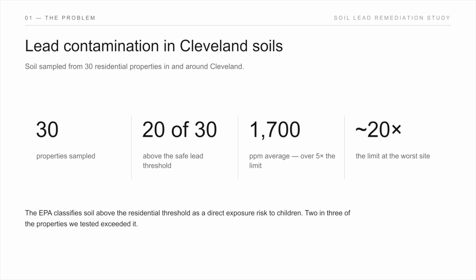That is more than the baseline in Cleveland. I don't want you to think that every site in Cleveland is that bad, but it's generally due to these acute toxins that are near crumbling infrastructure. So if there's lead-based paint chipping off the building, getting into the soil, that's where you're going to find these concentrations that are like off the charts like this. 20 out of 30, that's a pretty bad hit rate for what we were noticing there, but it's kind of indicative. So we're doing more testing. We're going to see, was this an outlier, but a really bad start to that.